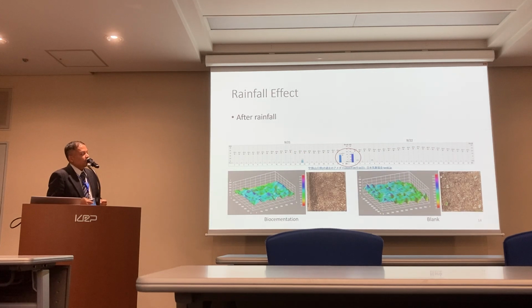And there was some big rainfall after that experiment. For 2 continuous days there was rainfall, and after the rainfall we checked the erosion of that slope. We took photos and did some image analysis, and obviously you can see that for the biocementation slope, the surface is much stronger, okay?